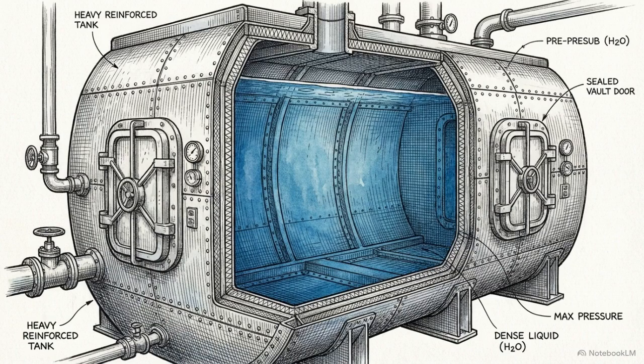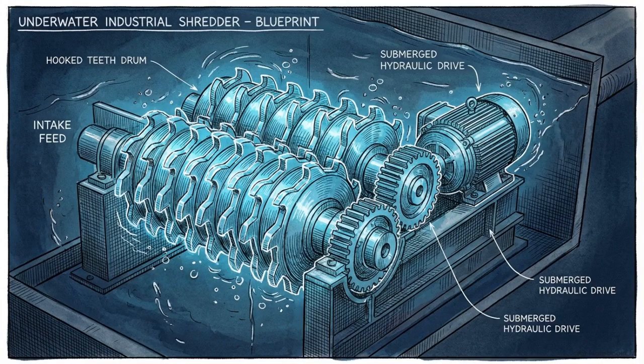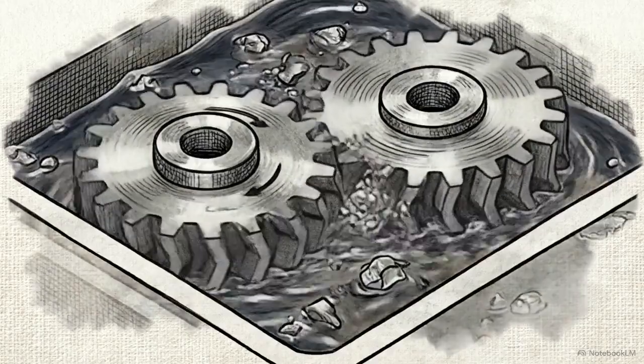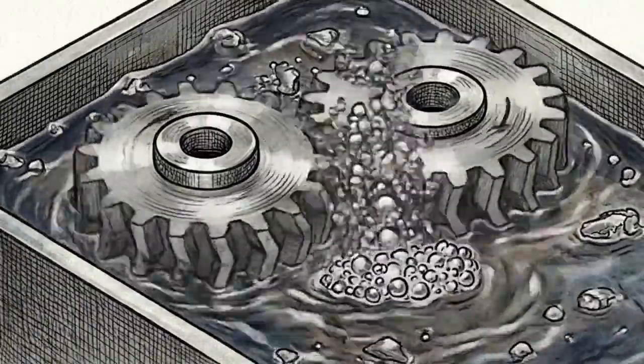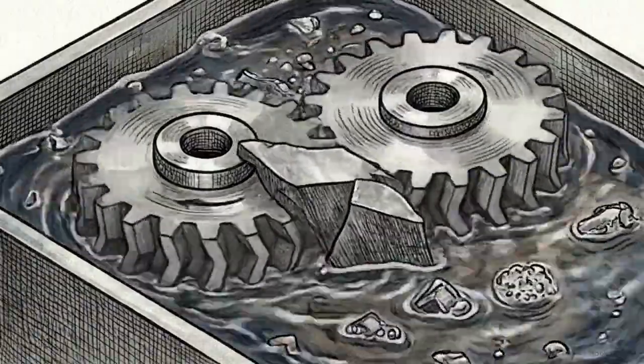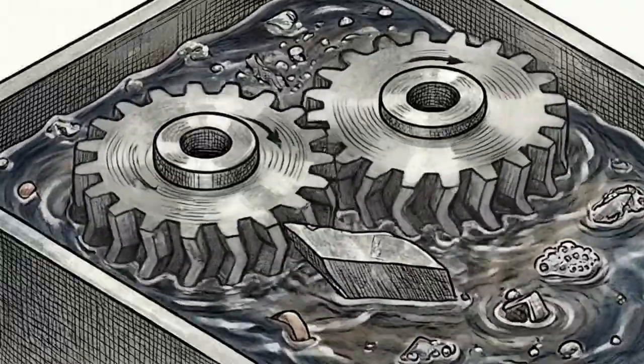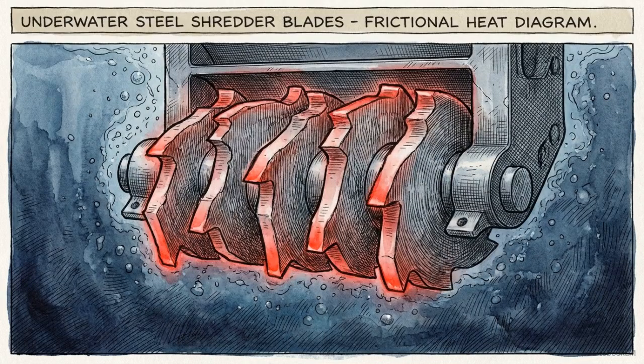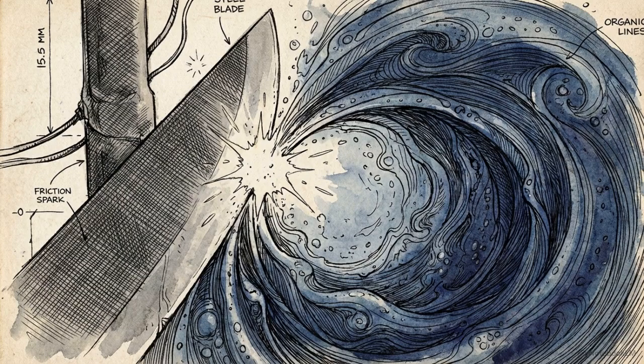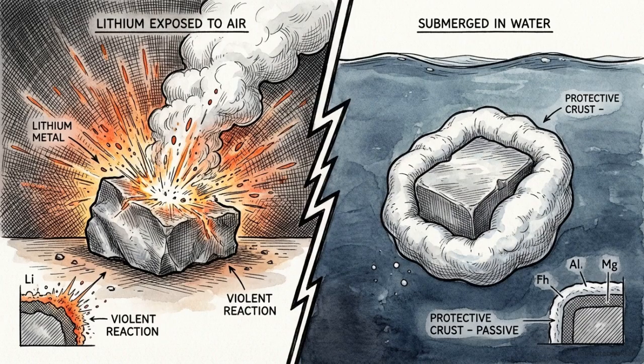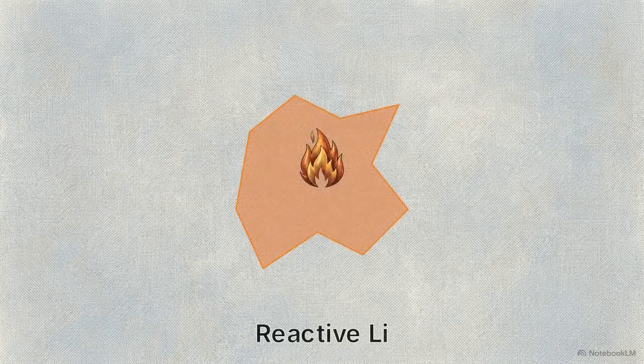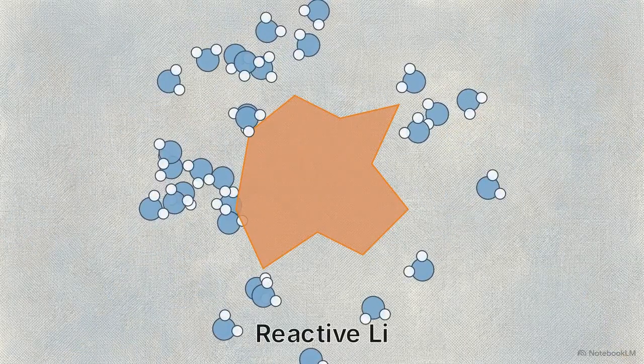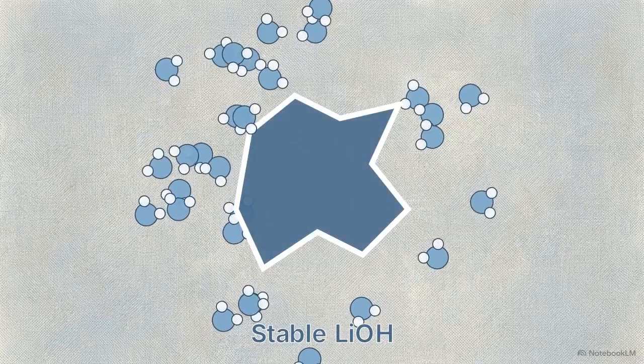the first place. The industry's highly scalable answer to this threat is submerged comminution, commonly known as wet shredding. In this process, the violent mechanical action of heavy steel shredder blades tearing the battery casings apart happens completely submerged underwater. The liquid bath acts as a massive thermal sink. It instantly absorbs the immense frictional heat and quenches any localized sparking before the electrolyte has a chance to ignite. The water also provides a critical chemical passivation benefit. Any highly reactive elemental lithium is safely oxidized by the surrounding liquid into a stable, less reactive state.